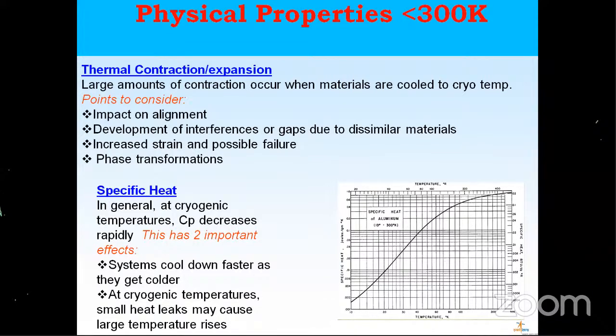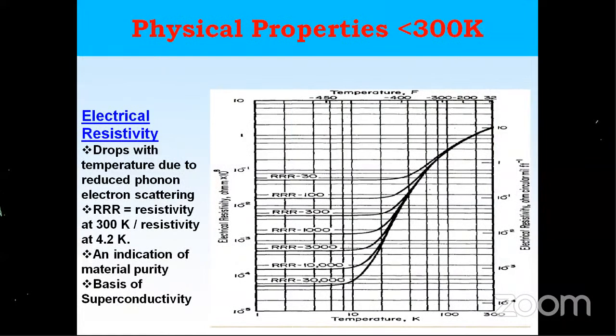Then another important thing is the electrical resistivity. At room temperature it may not be noticeable. When you go to low temperature, the purity of the material becomes very, very important. So there is a residual resistivity ratio, RRR. It is the resistivity at 300 K divided by the resistivity at 4.2 K. This shows the purity. The purer the material, the higher its thermal and electrical conductivity and the lower its electrical resistivity. This is the basis of superconductivity for metals.